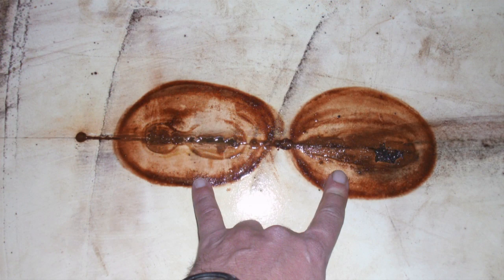If holiday, pinhole, or Jeep testing is not performed and there are undetected voids in the coating or lining system, then the contents of the tank, vessel, rail car, or pipeline may attack the exposed substrate and cause pitting corrosion, loss of section, and eventual perforation of the substrate. In addition, the contents may become contaminated with the corrosion products and the coating and lining debris if deterioration occurs.